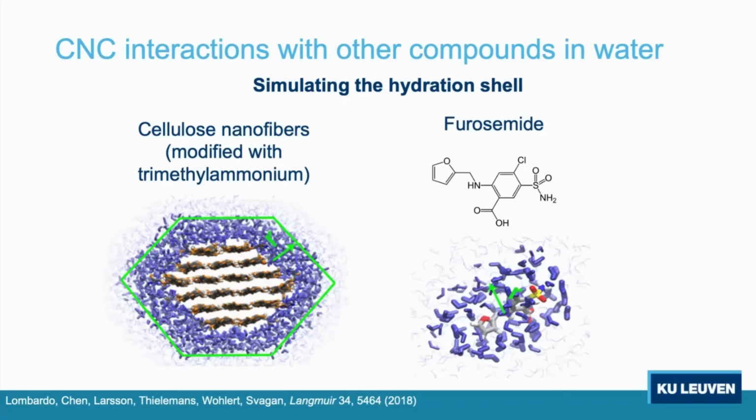And what we see is that along the hydrophilic planes, we have more polar interactions, so we have a higher enthalpy of interactions, but we have a much lower packing, so much less water molecules on these faces. If you look at the hydrophobic planes, we see that the water molecules are packed in a much more structured way, so they have a very large reduction in entropy,